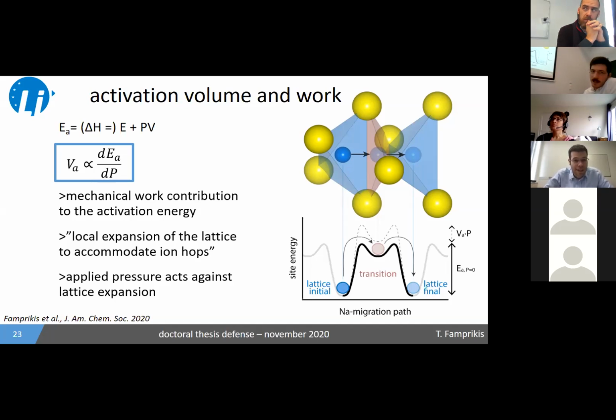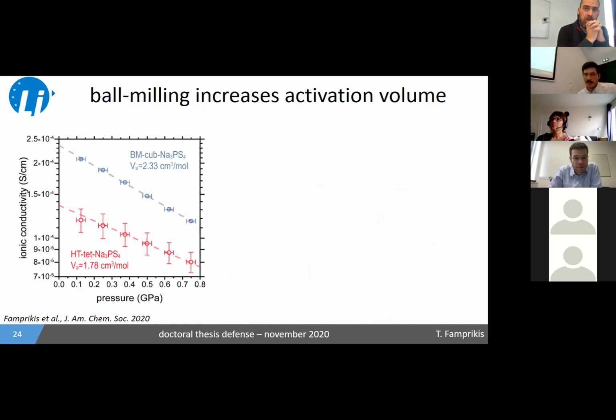Yes, the question is, how does your defect formation enthalpy change under pressure? Because now we're here at really high pressure. So basically you can play the same game with the volume. You can have an activation volume for migration and an activation volume for defect formation. So I think where you're going with this is that this activation volume and this difference that we see here could also be linked to formation more than migration? Correct. Yes, I agree. Okay.